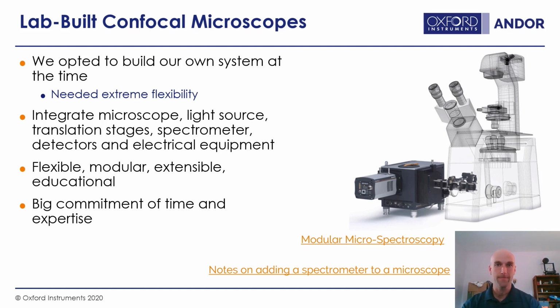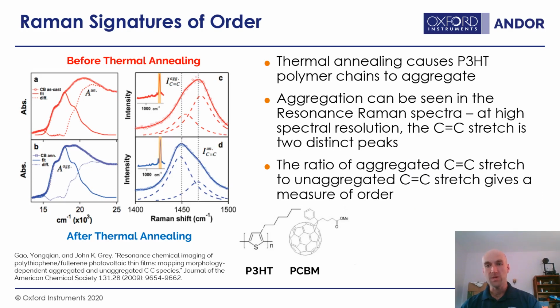So what were the spectroscopic points that we were actually looking for with this hyperspectral microscope? Well, specifically in this system, which is another conjugated polymer donor acceptor blend, this is P3HT here. P3HT thermally anneals, or can be thermally annealed, which causes the polymer chains to aggregate. And so that aggregation can be seen in the resonance Raman spectra quite clearly if you have high resolution resonance Raman spectra that you can record. So if you're looking at that spectrum with sufficiently high spectral resolution, so here is the overall spectrum, which is dominated by a peak in here. That's a carbon-carbon double bond stretch. That is actually two overlapping peaks if you look at it with a high resolution.